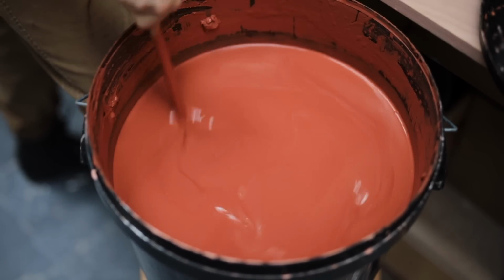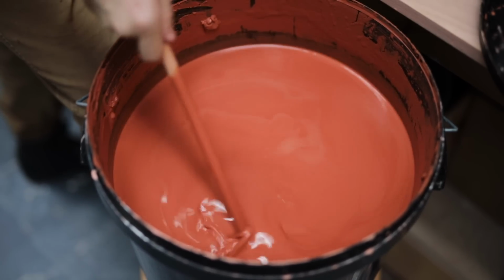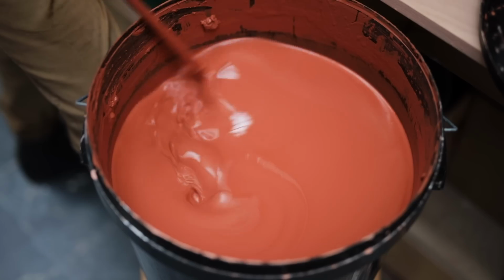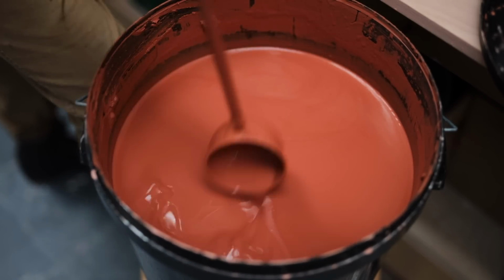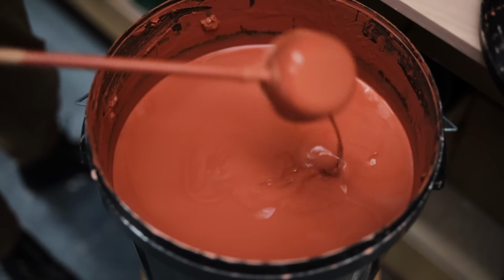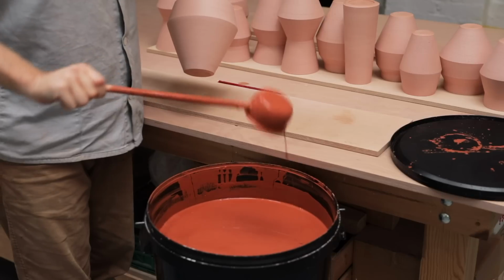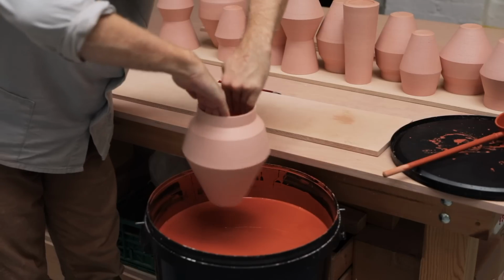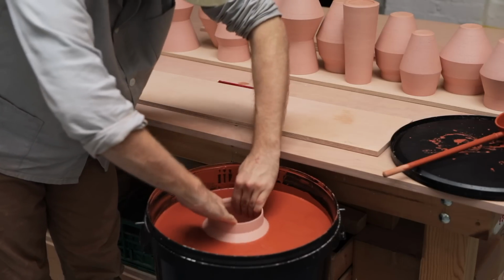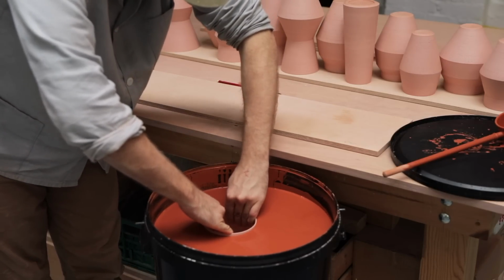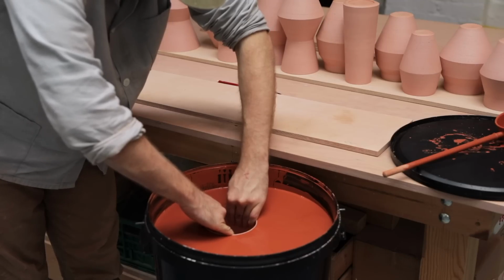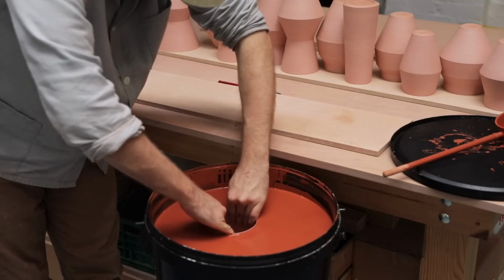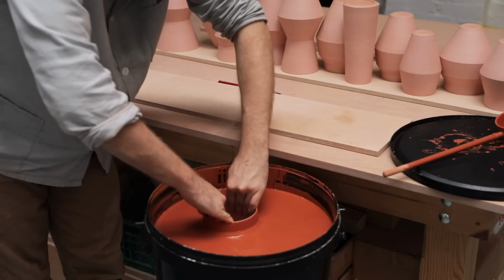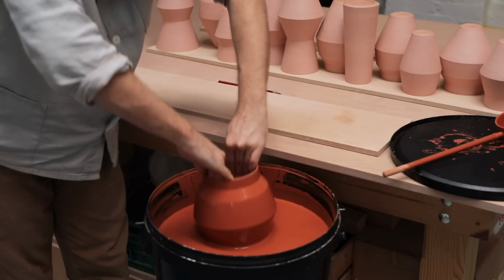Some glazes need to be thicker, some applied more thinly, and this particular recipe settles quite quickly in the bucket, so before it can be used, it needs to be mixed thoroughly. I then hold the pot from the inside and quickly push it into the glaze until it comes to the rim. It's held there for a number of seconds so it can draw in a thick enough layer, and then I lift the vessel out and shake off some of the excess around the base.